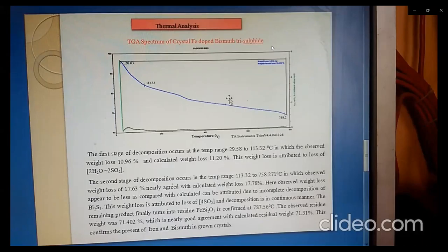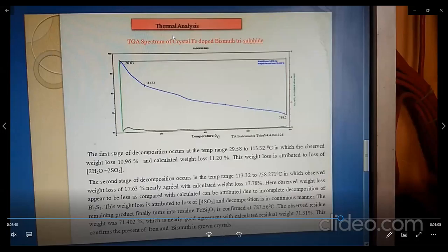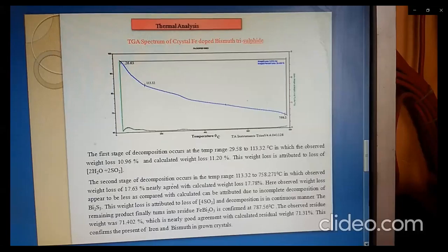The second stage of decomposition occurs in the range 113.32 to 758.271 degrees Celsius, in which the observed weight loss of 17.63% nearly agrees with the calculated weight loss of 17.78%. Here, the observed weight loss appears to be less as compared with the calculated, which can be attributed to the incomplete decomposition of bismuth trisulfide. This weight loss is attributed to loss of 4SO2, and decomposition is in a continuous manner. The remaining product finally turns into residue.